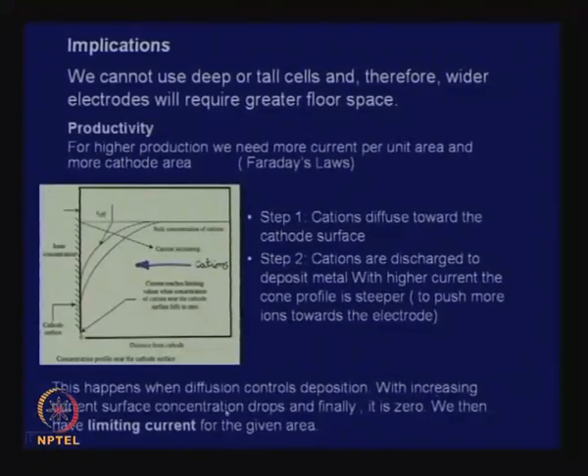So, in any given cell, if it is a diffusion controlled process, which most metal deposition processes are, there is a limit. And this limiting current concept is of vital importance in electrometallurgical operations. So, I will quickly go through this again. For higher production, we need more current per unit area, for more cathode area. Step 1 is cations diffused towards the cathode surface. Step 2 is cations are discharged to deposit metal. With higher current, the concentration profile is steeper to push more ions towards the electrode, and then finally, we end up with the limiting current.